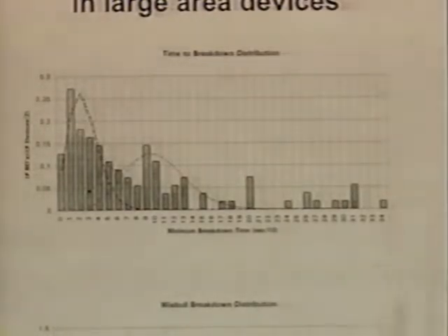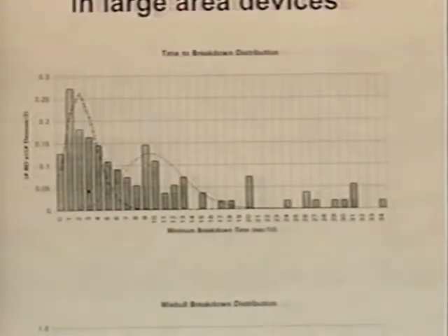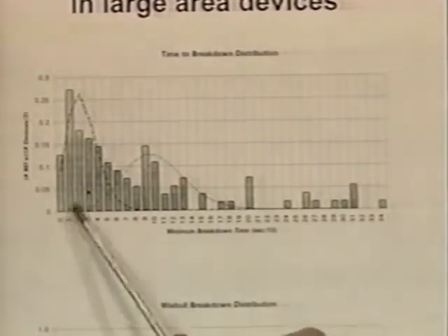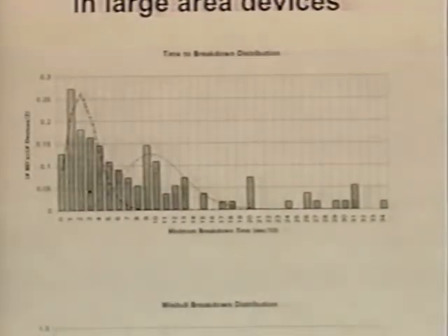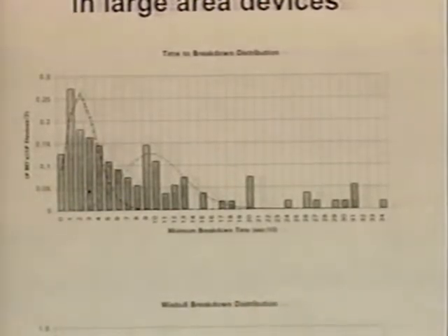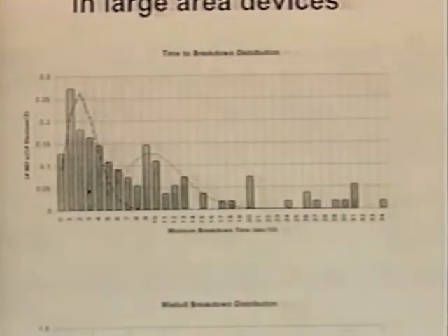And in fact, you can just try to apply Poisson statistics and say, well, you got one breakdown with a mean time of 10 seconds and one breakdown with a mean time of 100 seconds. And the curves just fit right on there. We've got a statistically controlled breakdown effect that has to do with the defects. You've even got a whole spectroscopy here. You can say, oh, you got one type of defect here, one type of defect here, but nobody cares because you want to look at the intrinsic device.